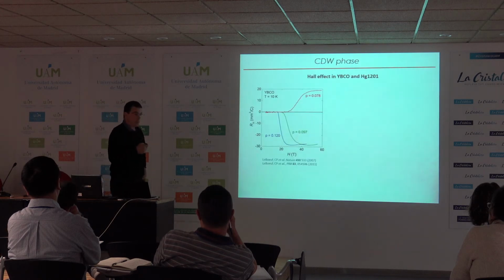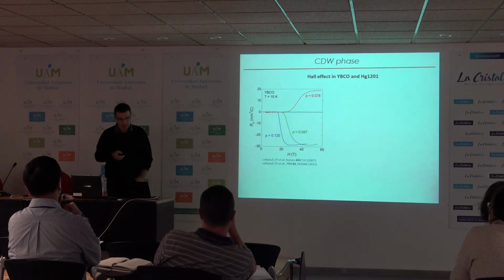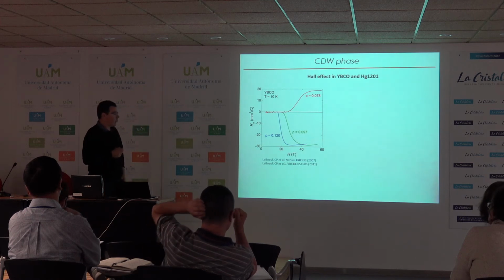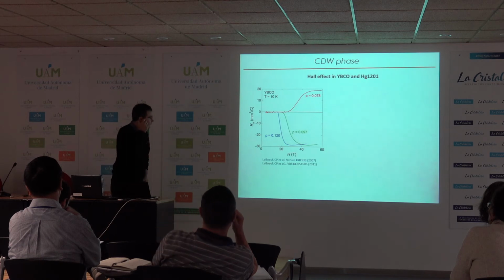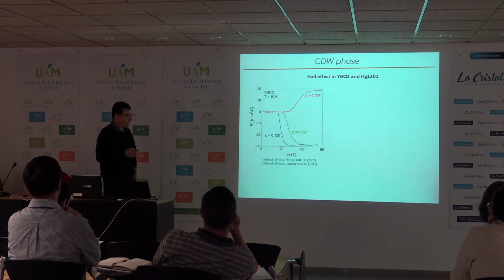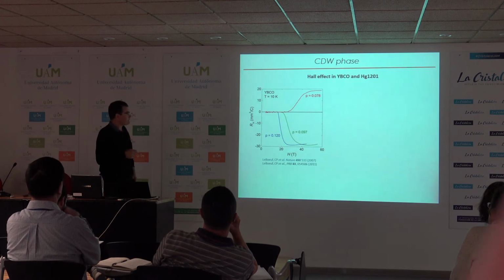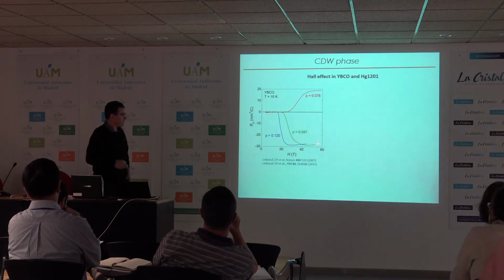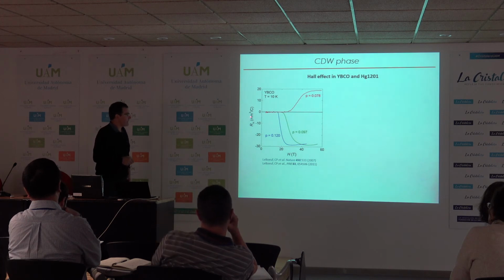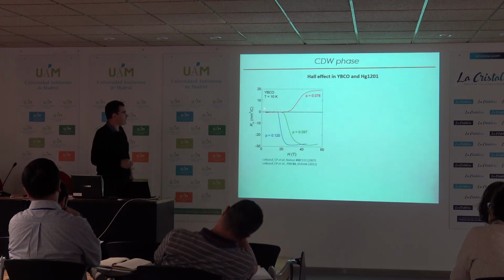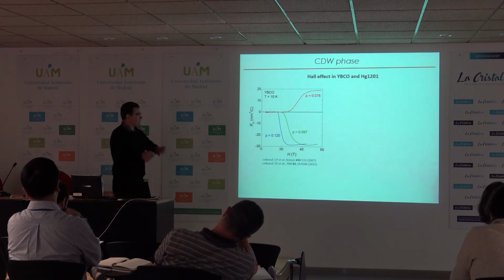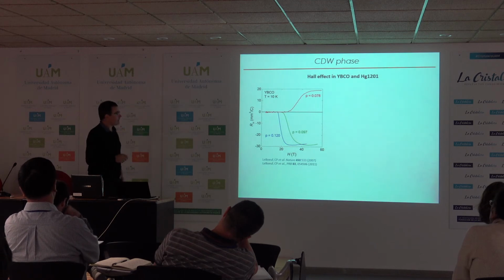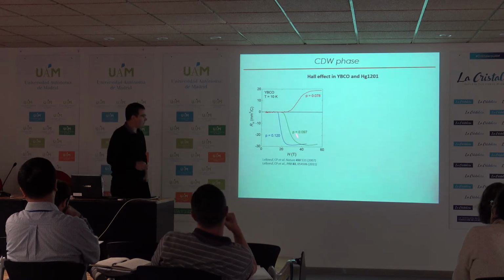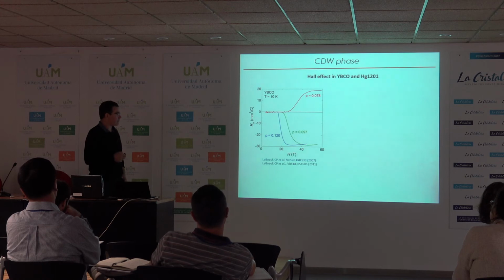So another transport property that has been very important for charge density wave is Hall effect measurement. And what we have shown actually is when you enter the charge density wave phase, the Hall coefficient becomes negative. So this is the Hall coefficient versus magnetic field measured at low temperature, at 3 different dopings. At this doping, we are slightly outside of the charge density wave, and you see that as soon as you go inside the charge density wave, the Hall coefficient becomes strongly negative.